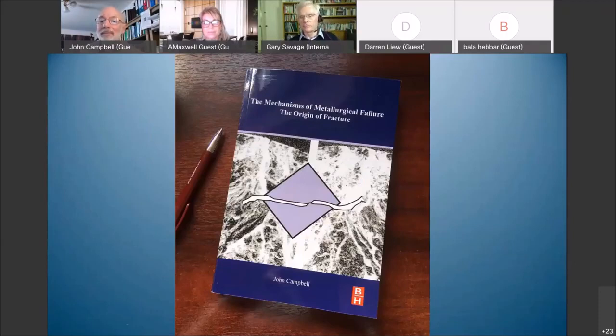I won't spend too long on this. The short answer is yes, we have. And it's my aim to prove that first at CSIRO, casting aluminium. And then I'll make those molds available to any foundry that wants them. And you pour your metal the way that you treat it, and you can pour it into your standard Australian standard test mold. I can even print them for you if you haven't got a pattern, an E-type mold, and then pour it into John's mold and see if you get any different results. If you do, then it's due to John's methods. It's a good way to quantify it. Maybe I'll leave it at that, and this will be a topic for further discussion throughout the AFI later on.